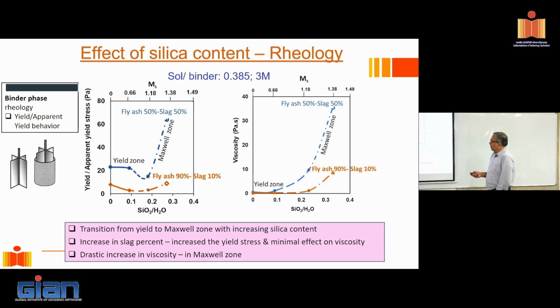So I'm showing you here data from two different pastes, one fly ash and slag in 90-10 proportion, another fly ash and slag in 50-50 proportion. But you notice what happens when I increase the silica content. Here, initially I get a yield type response, and then as I increase the silica content, it becomes a Maxwell type response. The peak resistance continues to increase. Okay, so what happens then? Whatever I'm getting as the peak resistance, that resistance is increasing, but it's a Maxwell type response. It will continue to deform. And the same thing happens for both of these, which means that, yeah, absolute values may vary, but it really doesn't depend upon the composition of the binder that I'm using.